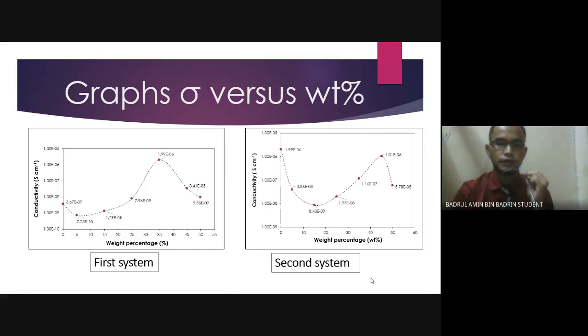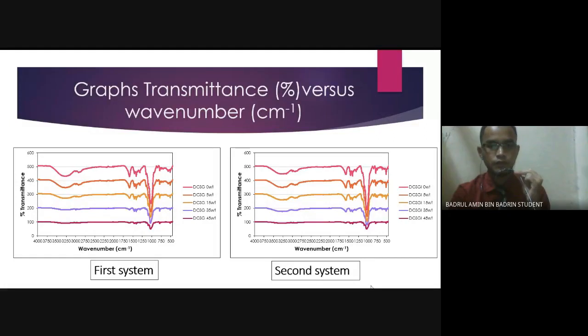Next is the graph for second characterization, Fourier transform infrared spectroscopy. The characterization is focusing on certain functional groups, and the effect from the hybrid of more elements in the system. So in this case, the blend polymer of CMC and dextrin from potato starch is introduced with plasticizer glycerol for the first system, and together with ionic liquid for the second system. As you can see, the bending in the graph prove that there is a salt effect that takes place in the system when it is being introduced.